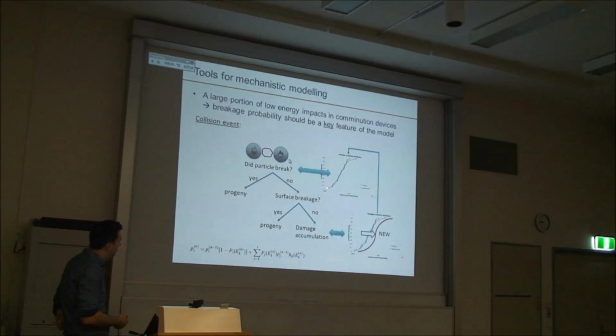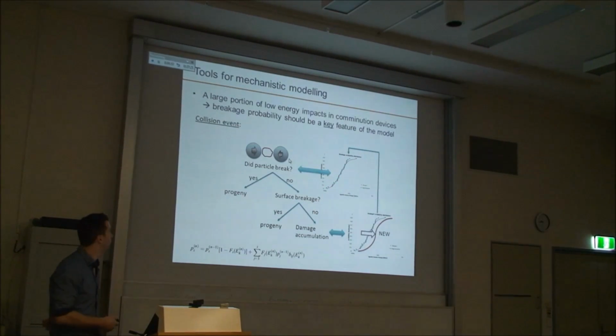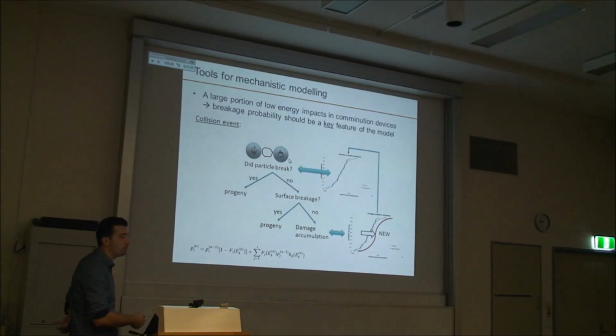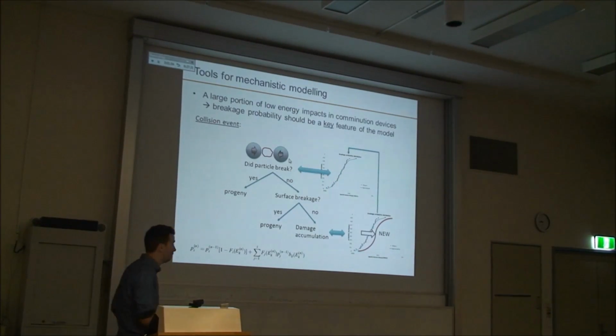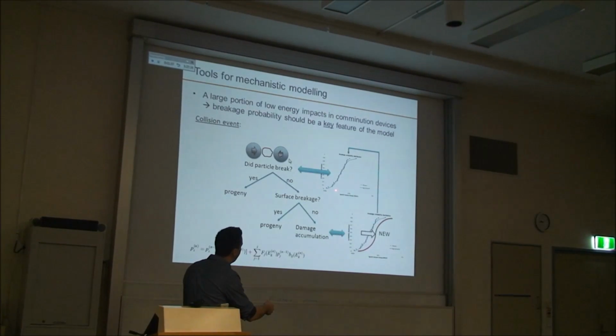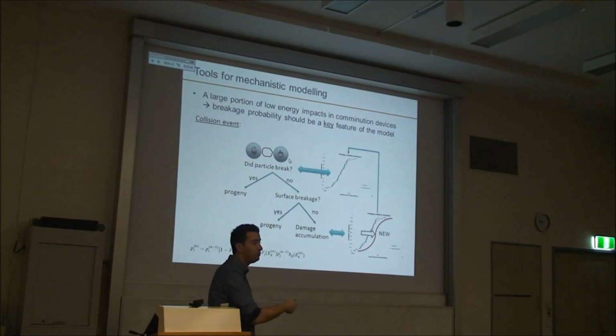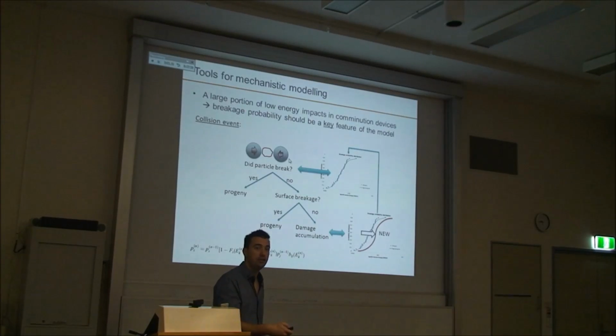By breakage probability, what people have shown is that this distribution of strength is exactly the same as the probability. So I've measured the particles independently here. Each one has a different value. But if I take the same sample, and if I now apply exactly this energy here, by impacting all the particles, what happens is that you will have exactly 20% broken. Okay? So you can already, with this curve, predict what the breakage probability will be. That's just because statistically in the sample you have 20% of the particles that have a fracture energy below this energy, and 80% that have a fracture energy more than this energy. So you're going to need to apply more than their fracture energy to break them. Okay?